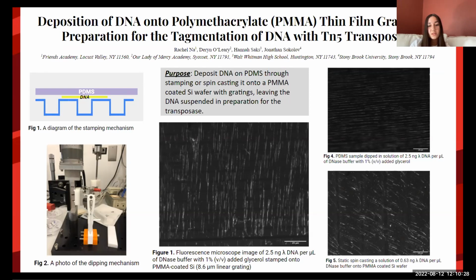The method we used to dip the samples of PDMS is seen in figure 2. We imaged our samples with a Leica microscope, and if the DNA appeared to be stretched out, we stamped the sample onto a PMMA-coated silicon wafer.